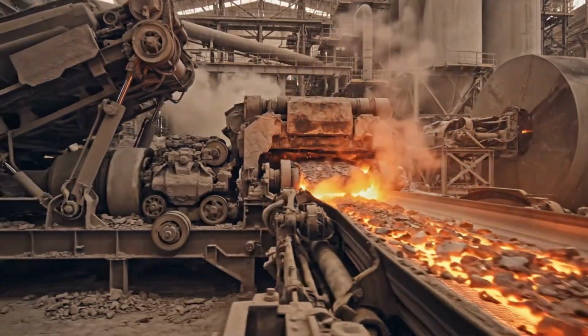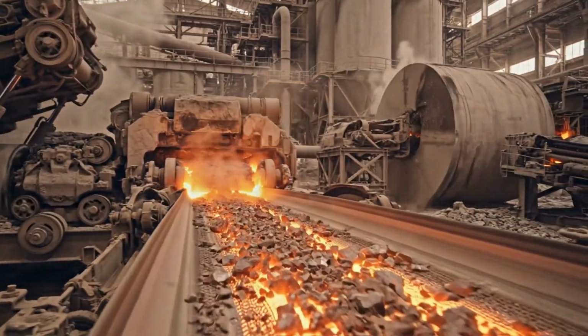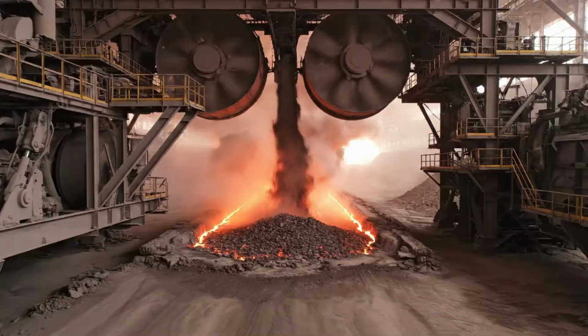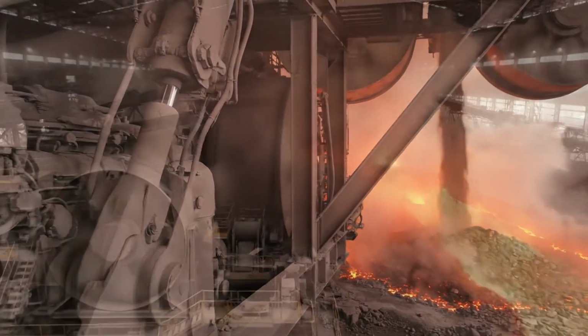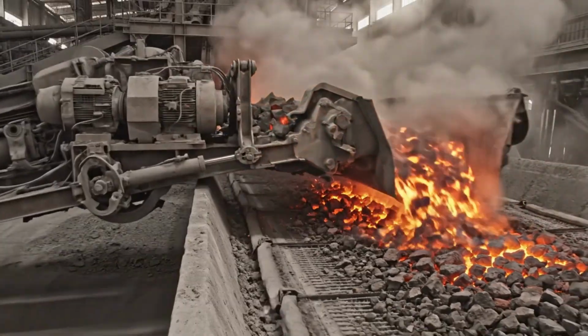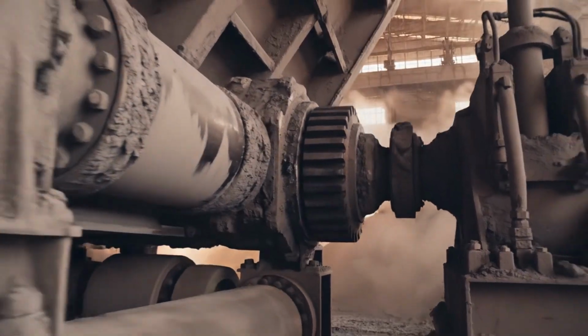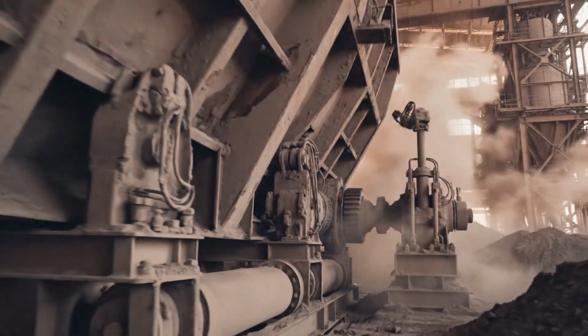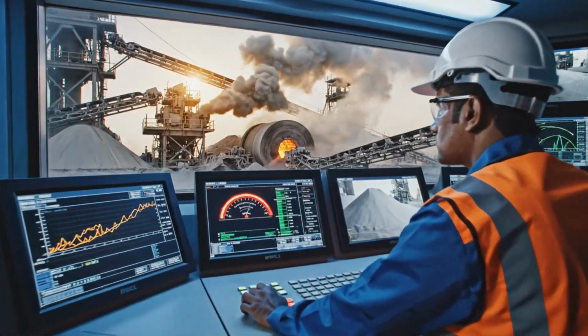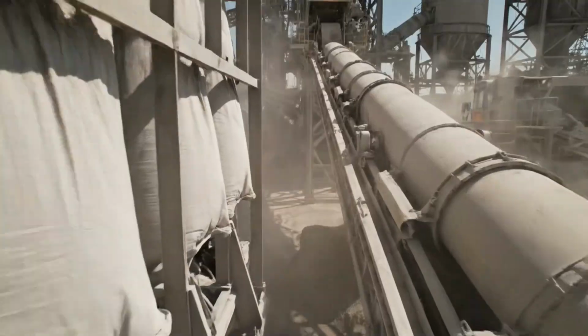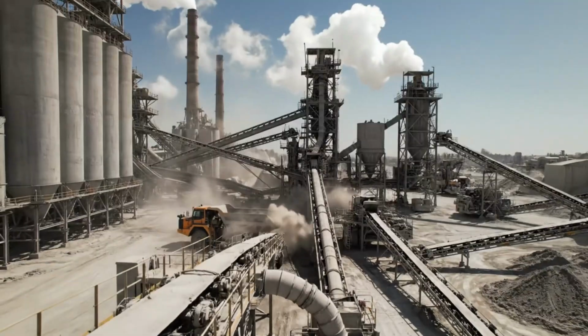As clinker leaves the kiln, it must be cooled rapidly. Clinker coolers use powerful airflows to reduce the temperature. This rapid cooling stabilizes the clinker and allows heat to be reused in the process. Once cooled, the clinker is transported to large storage silos or domes. Here, it waits before the final grinding stage.